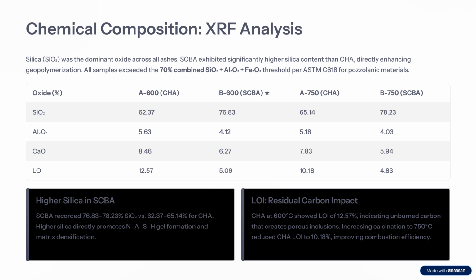So SCBA records a higher silica percentage, up to 78% versus 62% for the CHA. Higher silica directly promoted N-A-S-H gel formation and matrix densification. For LOI, the residual carbon impact: CHA at 600 showed an LOI of around 12%, indicating unburned carbon that creates porous inclusions, and increasing calcination to 750 reduced CHA to 10%, improving combustion efficiency.